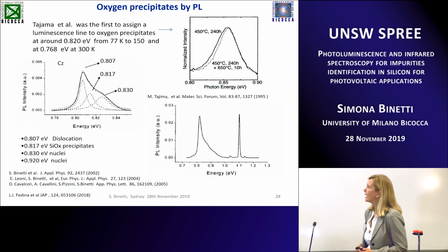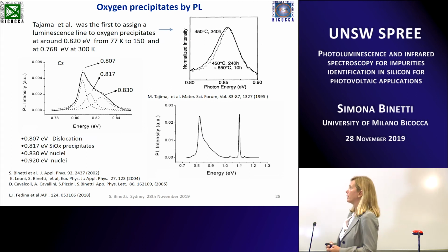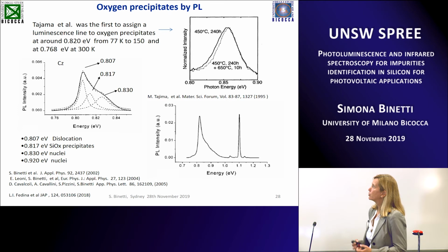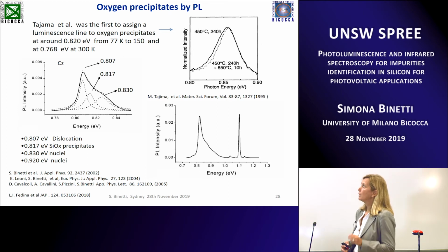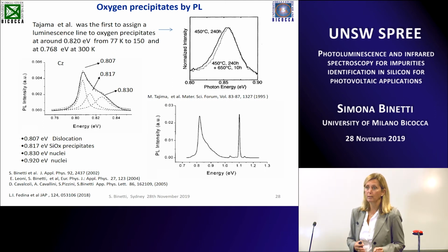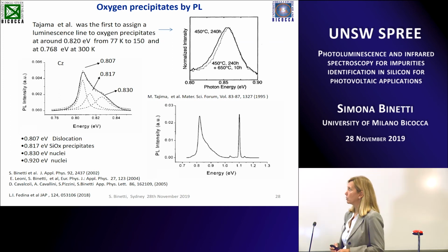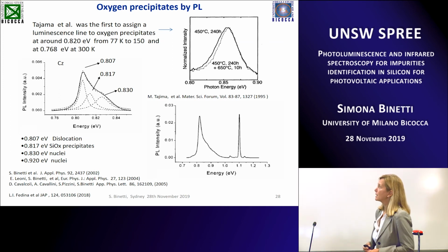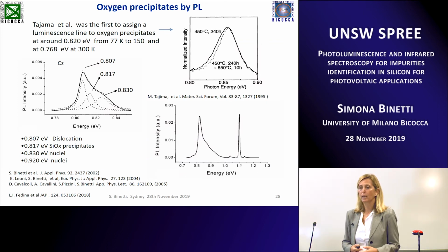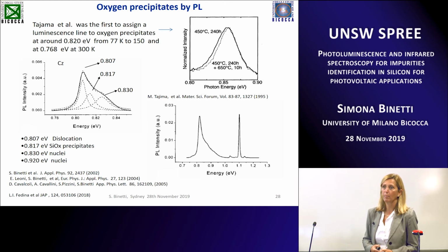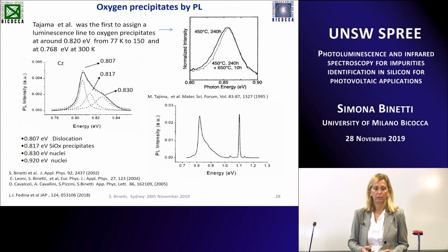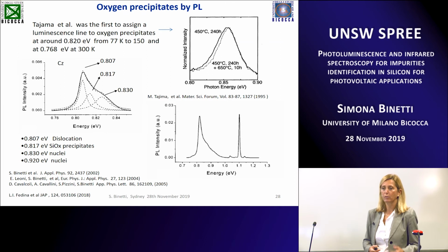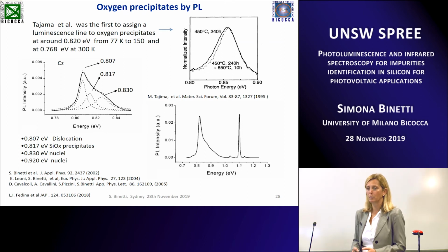This is work that we have done for many years in collaboration with the Japanese group, because Professor Tajima was the first to assign a luminescence line only to oxygen precipitates and not to dislocation, and to distinguish between a luminescence line related to oxygen precipitates and to dislocation. And this work was carried out also by us in a series of different papers. We did a very long investigation on different types of Czochralski silicon samples, treated at different temperatures, in order to have more or less all types of oxygen precipitates: nanoprecipitates, oxygen precipitates and dislocation.